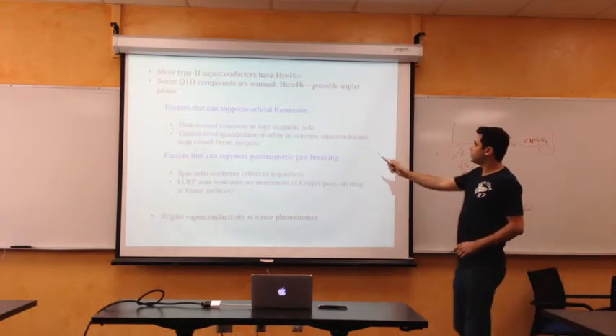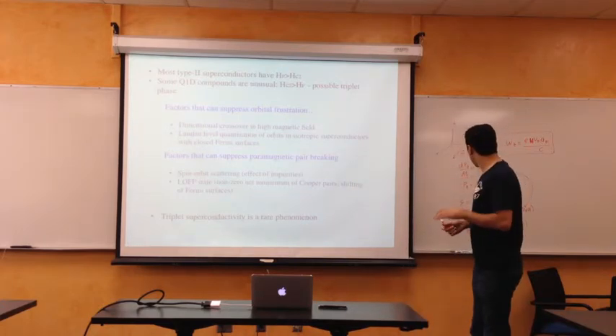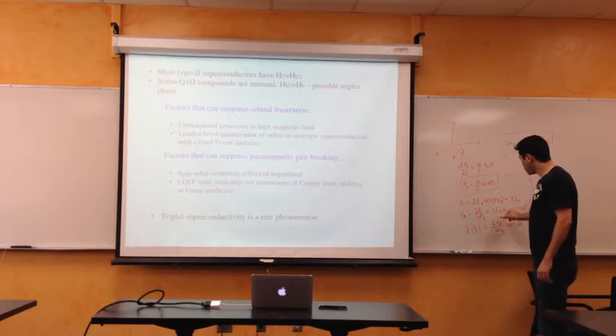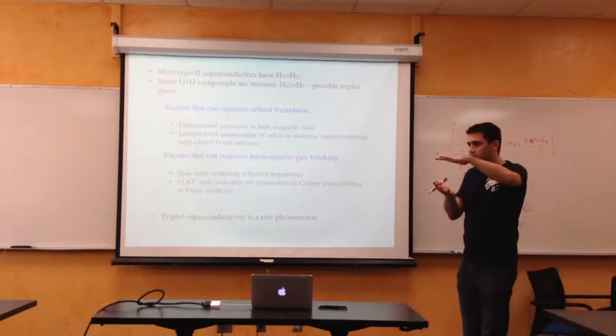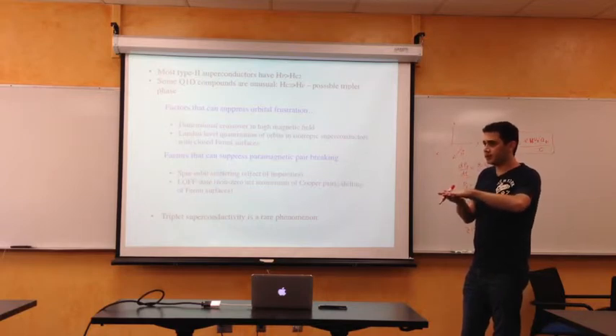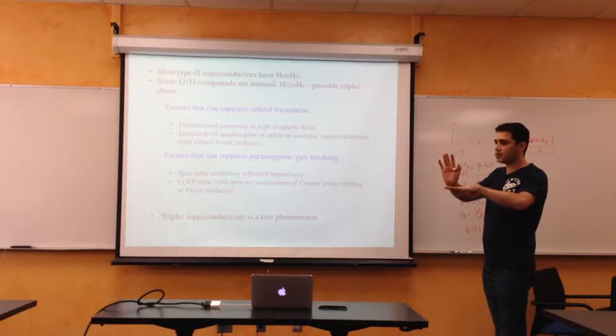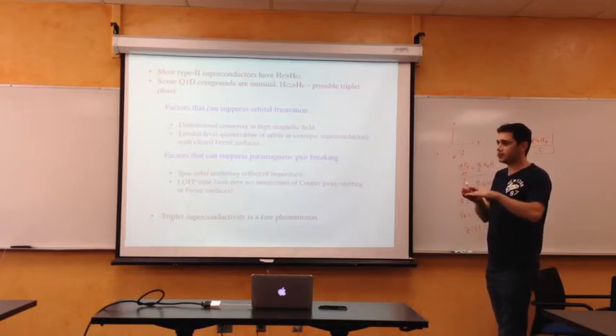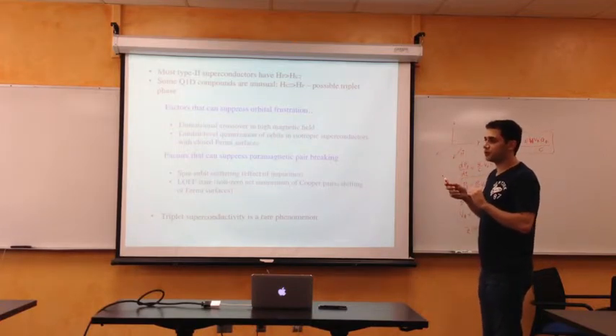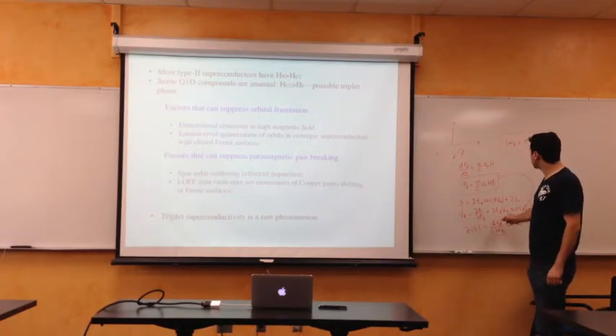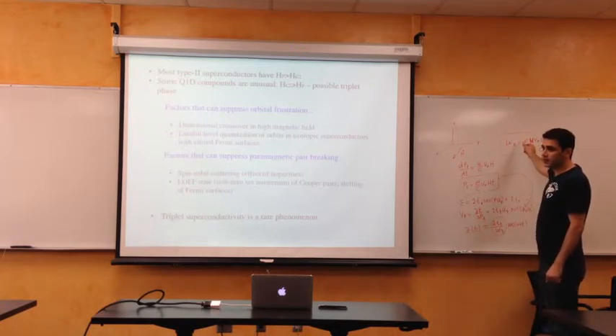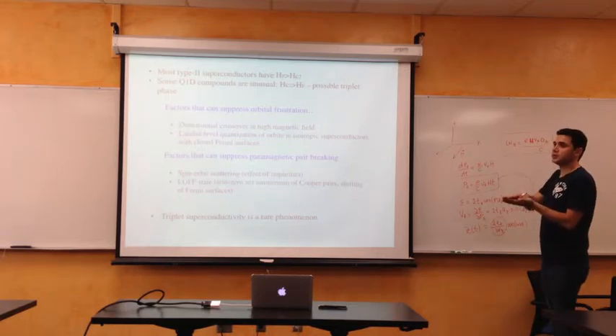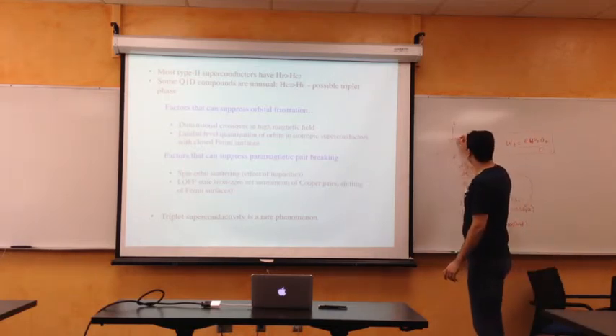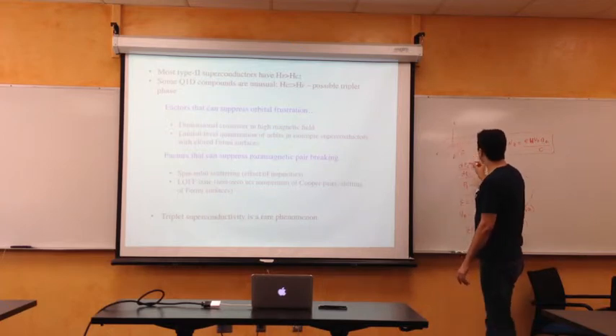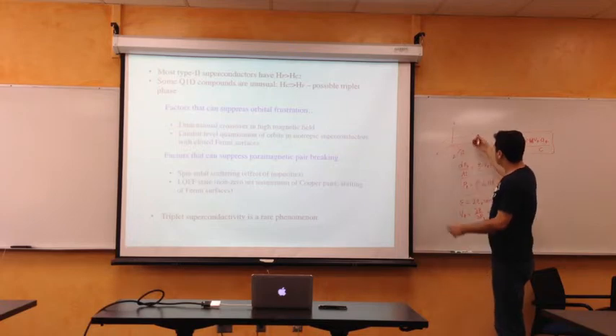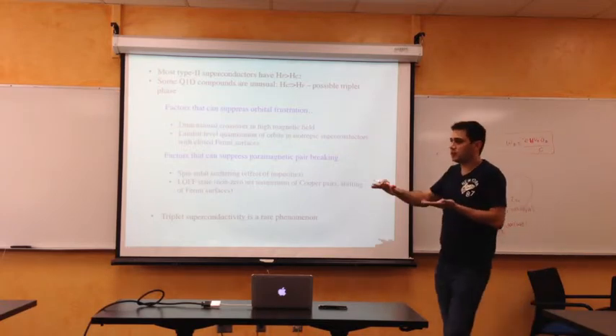So you can see that when the magnetic field is very large, this ratio becomes smaller and smaller, and therefore the electrons are confined to these two-dimensional planes. So the flux through the superconductor essentially doesn't kill the Cooper pairs, because this is what's called dimensional crossover - the amplitude is inversely proportional to the magnetic field H. If we make H very large, we essentially get 2D superconductivity. In a crystal like this, electrons are confined to the two-dimensional plane, so the magnetic field essentially has no flux on a flat plane.